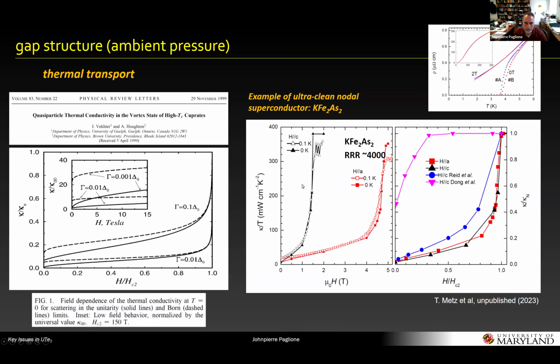But first of all, I just want to point out that it's not unusual to have a very flat, very slow rise in thermal transport at zero temperature as a function of magnetic field. This was pointed out early on in theory by Ilya Vekhter and company in the context of the cuprates, where depending on the parameters, you can see that there's a very slow rise of the normalized thermal conductivity until you get very close to upper critical field, and then it jumps up. And in fact, I have data here, which we actually haven't published yet, on potassium iron arsenide, which is an extremely clean system, RRR 4000, TC of about, sorry, 3 and a bit Kelvin.